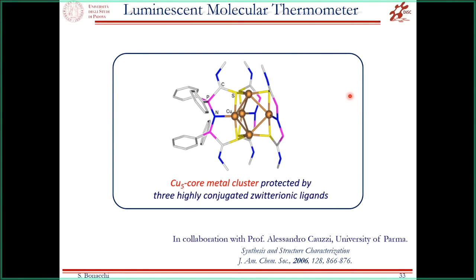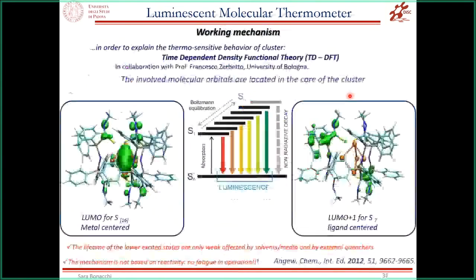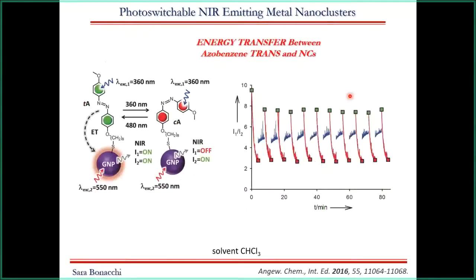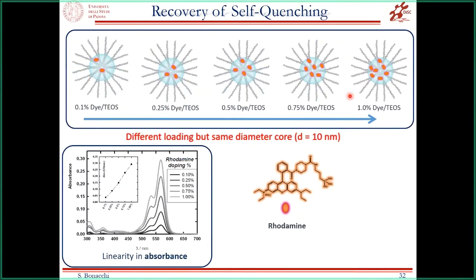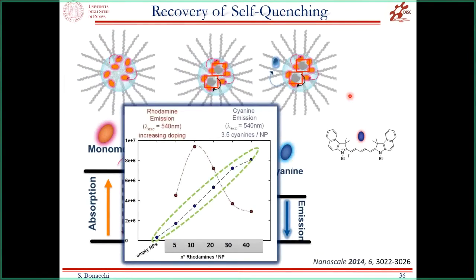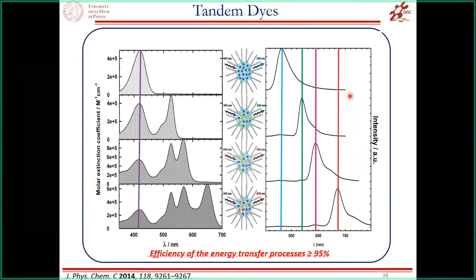Okay. Especially for your institute, for the last part of your topic, the silica nanoparticles doped with dyes, I see that you can control all this energy transfer and you can eventually modulate the emission color, right? You can have a combination of different emitters present in your sample, and you can tune this very well. So for other types of application, I know that competing with phosphors for lighting will be difficult, but for precisely designed OLEDs, because you are using electroluminescence now, right? I mean, a combination of this. So have you, for instance, tried to put this in a kind of device architecture to have this type of device?